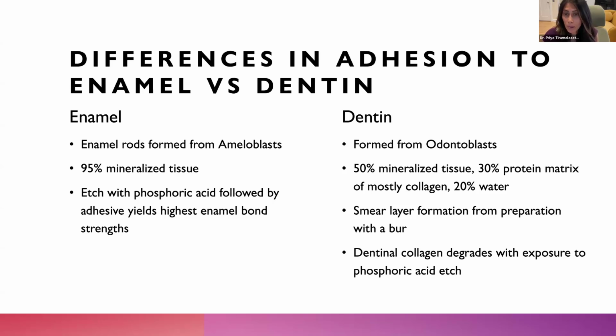Dentin, however, is very different. It's only 50% mineralized tissue, 30% protein matrix of mostly a collagenous matrix, and then of course water. And dentin, the collagen degrades with exposure to phosphoric acid etch when it's as strong as 37%. So the etch that we use for enamel should be different from the etch that we use for dentin.